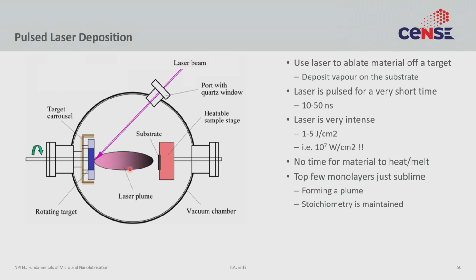So they actually form a laser plume which has plasma and gases. And that laser plume expands, deposits on the substrate and extinguishes. There is no sustained plasma here because it's just one shot. But then another shot of laser comes in, another shot of laser comes in. So every time you evaporate or ablate the top few nanometers of the target, which gives you an amazing amount of stoichiometric control, which allows you to deposit films that are otherwise very hard to deposit during sputtering and evaporation.